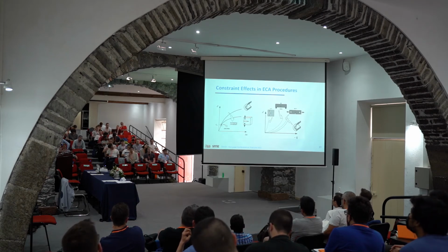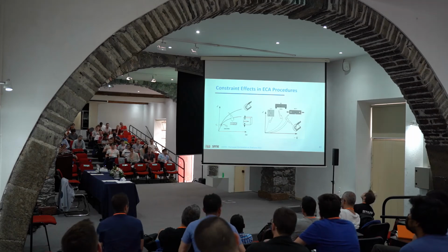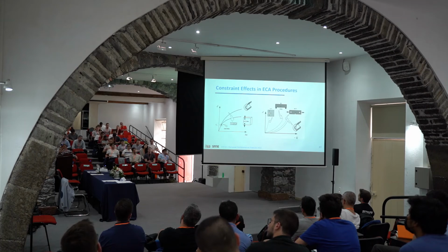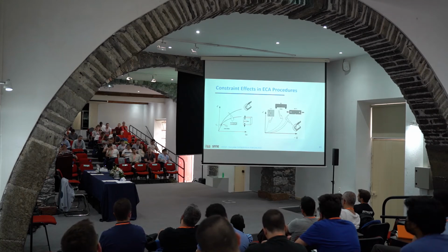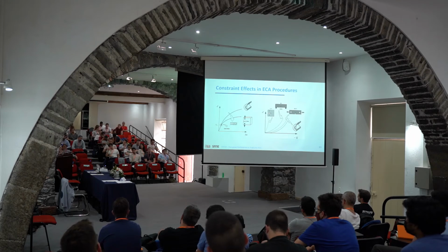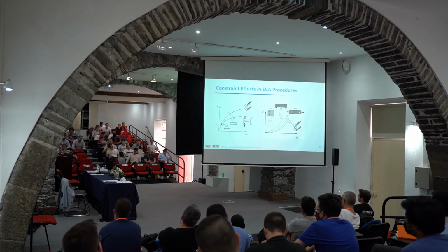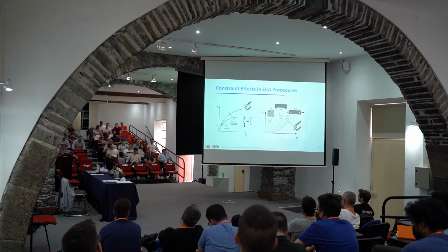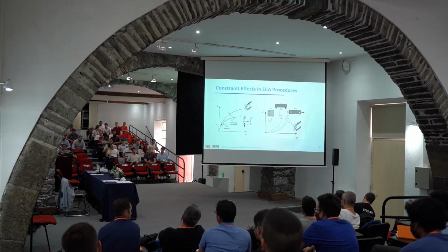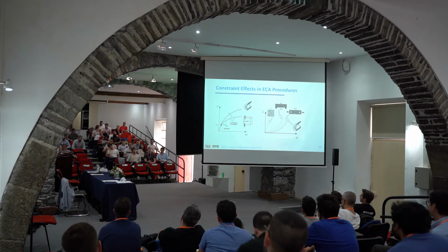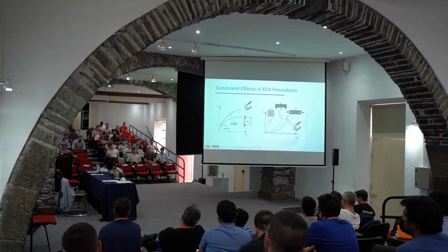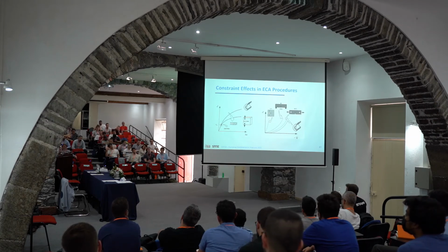You see here the CT specimen, the compact tension specimen. The compact tension specimen is probably the oldest specimen in fracture mechanics. If you go back to the 70s, the beginning of fracture mechanics, especially in the US, all those ASTM papers, Jim Rice, many others, you see a lot of experiments and analysis on the CT specimen. So the compact specimen is the most widely used geometry in fracture mechanics, and that's because it has high constraint. It provides very severe fracture toughness. That's why it's largely used. It's very conservative.